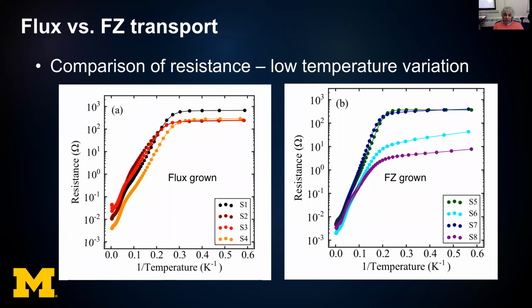Now, let me start with the raw data. This is resistance from the 8 samples that I'm going to focus on today. When you look at resistance, there is some variation because of the thicknesses, but overall, the samples, at least in the flux-grown set, are very similar to each other. And in the floating zone set, I show 2 samples that significantly deviate. They have a lot more conduction at low temperatures. The conduction appears not to be flat. There is some temperature dependence to the resistivity, and such behavior has been reported in some of the other floating zone samples.